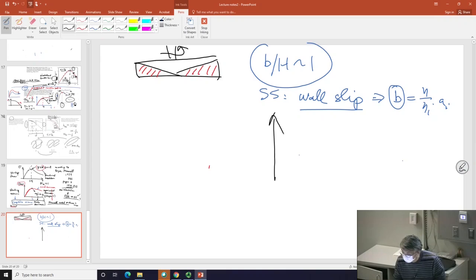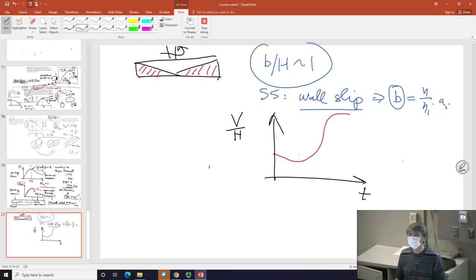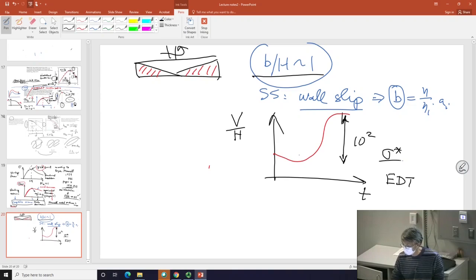Well, the rest is history, because we see, and I use this carefully, a big jump by applying a certain stress. We see maybe a 2 order of magnitude jump for a sample like this. That's impossible. We later realized that this is what we called the entanglement-disentanglement transition. And there, we further speculated that at least in this creep mode, maybe there will be no shear banding. I want you to connect that the initial motivation was wall slip, but separately, in parallel, we were aware of the Doi-Edwards prediction of shear banding, and also of the failure to observe shear banding up to that point.